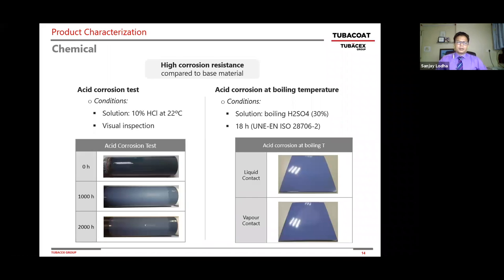This is just another example on the chemical properties. I took one example of hydrochloric acid and sulfuric acid. Over 2000 hours, with 10% hydrochloric acid at 22 degrees and sulfuric acid 30%, which is very corrosive, using the European test in both conditions, again, this Tubacoat material holds very well. There are many, many more tests we've done with molten salts, sodium hydroxide, you name it, and this holds very well in most applications. Next slide, please.